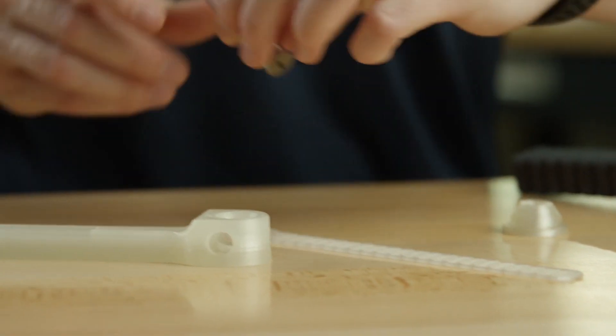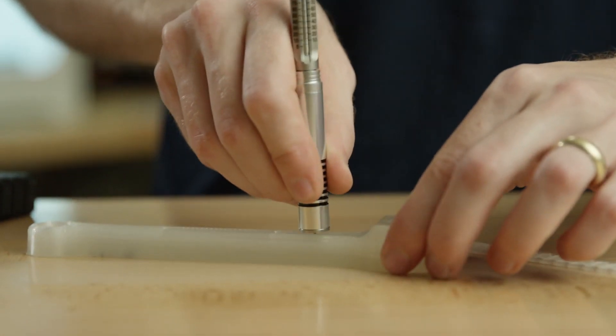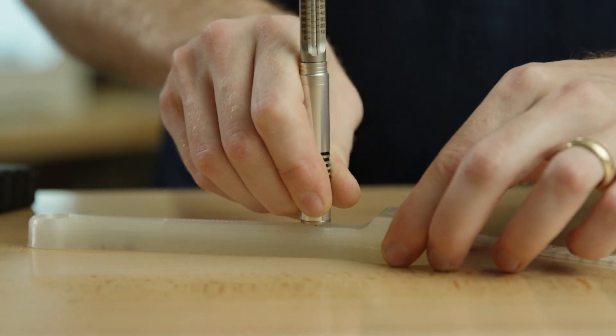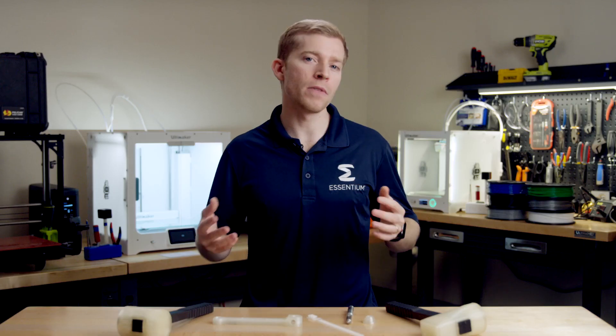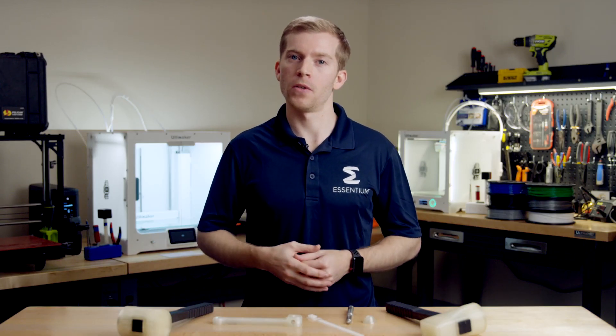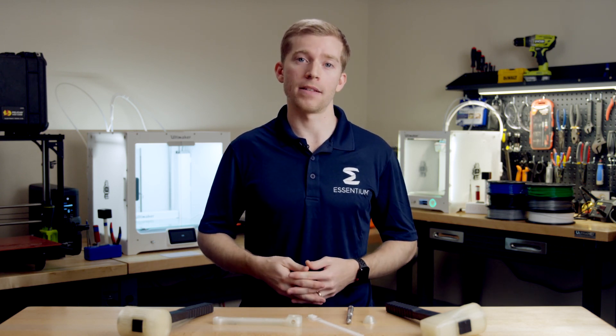These 3D printable rubbers can be made with a wide range of hardness values by altering the ratio of hard and soft segments in the polymer backbone when they're synthesized. The hardness of polymers is commonly measured with a Shore durometer scale. Essentially, a hardened steel rod is pushed into the material with a specified force, and the depth of indentation is measured. There are a few different scales used, but for flexible 3D printing materials, the Shore A and D scales cover the printable range for thermoplastics.